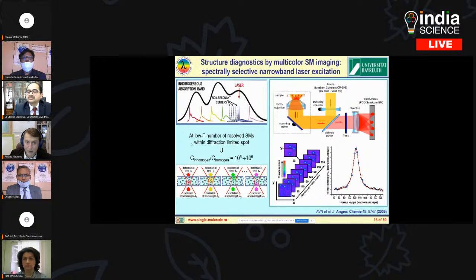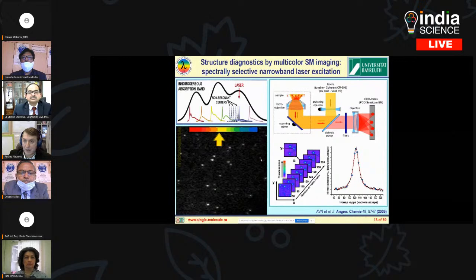You see the values of homogeneous width of our spectrum divided by homogeneous width for a single molecule can achieve values 10 to the 5, 10 to the 6. It means that I can resolve such a huge number of molecules within each diffraction-limited volume. And the idea of the experiment is very simple.